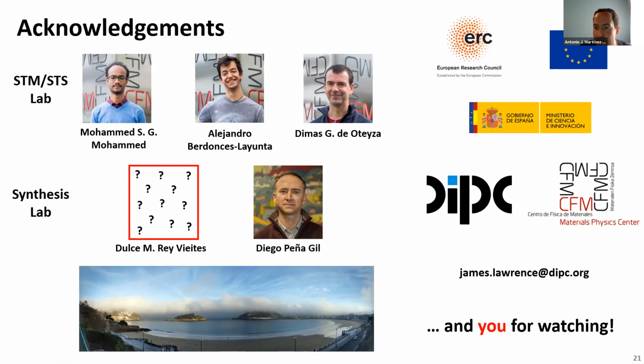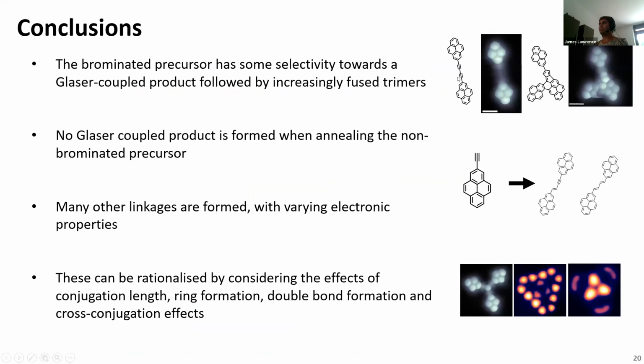There is one question from Bruno de la Torre. He asked, did you observe frontier orbital mixing as Pavel showed when the conjugation changes from triple to double bonds in your dimers? No, we don't. We see what appear to be strictly triple bonds in between these. For example, this is an image of the Glaser coupled dimer. You can see in STM imaging, the triple bonds typically appear as a dark feature, whereas in AFM they appear as a bright feature. And you can see here, for example, we have two dark features where these triple bonds are. I think if you had this mixing, you probably would have to change the conjugation of these pyrenes as well. So I'm not sure how favorable that would actually be.